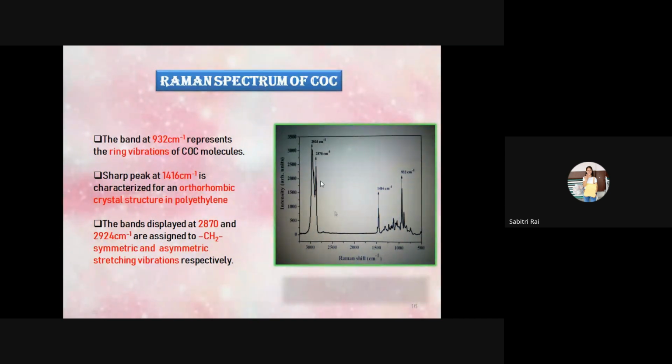We observe the peak at 2870 cm⁻¹, which is due to the CH2 symmetric stretching vibration, and at 2924 cm⁻¹, this is due to the CH2 asymmetric stretching vibrations.